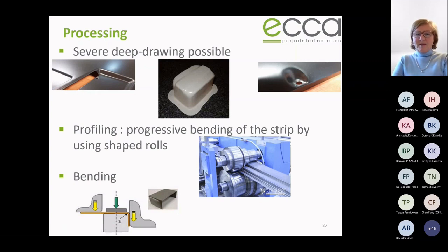So you see here with some example that even severe deep drawing is possible if we stretch, if we deform in 3 directions, no problem with the basis metal and the paint. Profiling is really well adapted to the pre-painted metal. We have a progressive bending of the strip by using the shape roll that's very soft. Step by step, we form the pre-painted metal very easily. The bending, absolutely no problem to bend, but here we have to be careful about the contact between the metal and the tooling, absolutely to protect the tools.